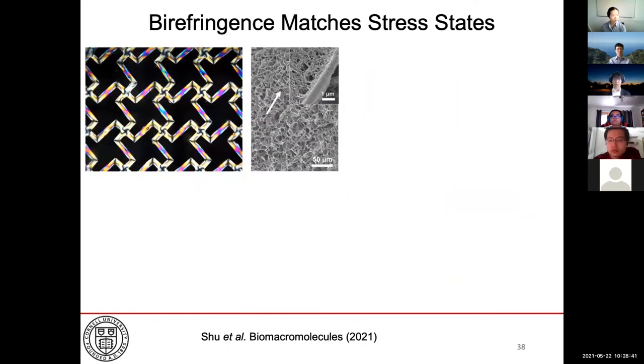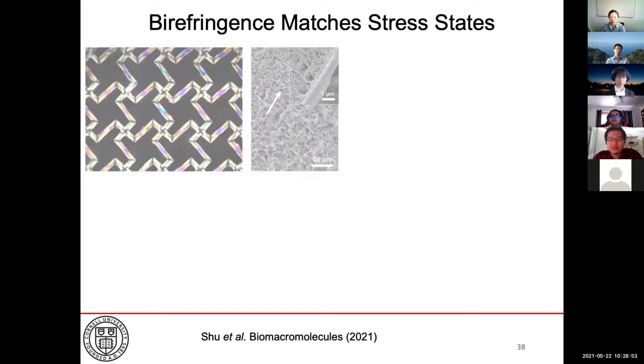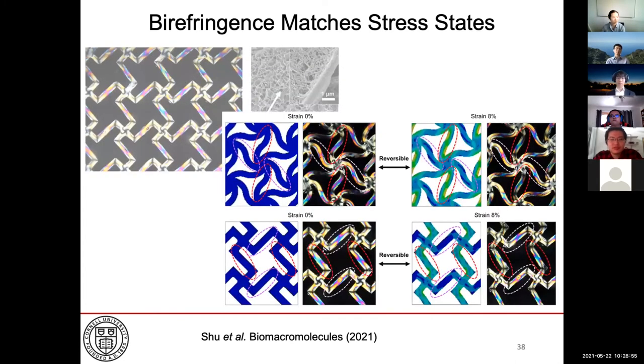And my collaborators were actually able to cast them into very interesting structures and be able to cast them such that we actually exhibit birefringence in the silk films. And these birefringence properties also strongly match that of finite element simulations that are again done by one of my collaborators. And basically we found a very strong correlation between the stress states of these particular structures, and this correlates very well with the finite element simulation.